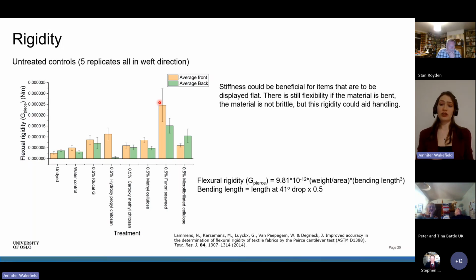Now, there could be debate about how much stiffness you want. Feeling all these wools, they were still very, very flexible, despite some increase in stiffness. If you're looking to drape the material to show how it was originally used, in cases where it's in good enough condition to be draped, you wouldn't be applying a consolidant in the first place. You'd be stitching it onto a backing material. So this is only really for cases where you'd be laying it flat anyway, because it is the most fragile of pieces. So that increase in stiffness is positive in those cases.